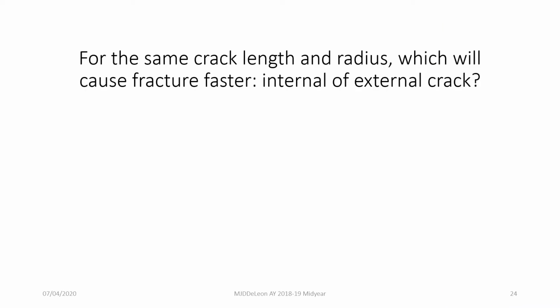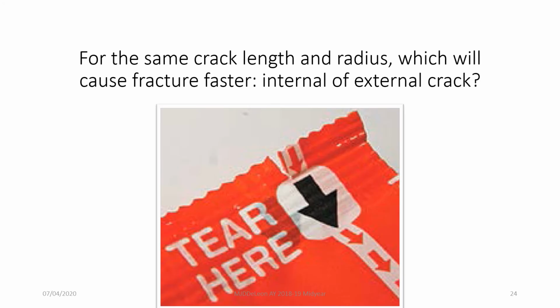So now think about this. For the same crack length and radius, which would cause fracture faster? A crack inside your material, an internal crack, or a crack outside your material, an external crack? So I'll give you 5 seconds to answer that, or you may pause the video. So 5, 4, 3, 2, 1. So the answer is an external crack would cause fracture faster.